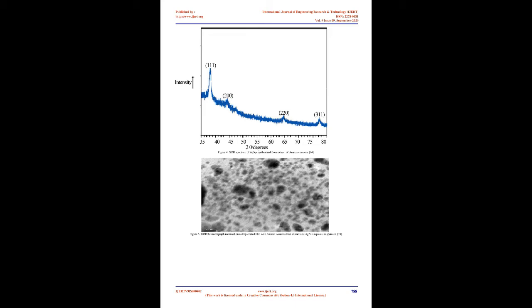The initial nucleation and the subsequent growth of initial nuclei can be controlled by adjusting the reaction parameters such as reaction temperature, pH, precursors, reducing agents (sodium borohydride, NaBH4, ethylene glycol and glucose), and stabilizing agents (polyvinyl alcohol, PVA, polyvinyl pyrrolidone, PVP, and sodium oleate) 61 to 63. This method is based on reduction of silver ions in aqueous or non-aqueous solutions using reducing agents.